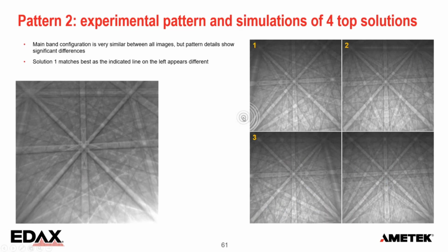Here's another one. On the left is the experimental pattern. And the patterns on the right already look a little bit more similar than what we had before. But now here in the experimental pattern, you have this band here and this one. They look about the same, but this one is a bit blurry in the middle. So this looks like it's one of the other types of bands. And when we look at the simulations, top and right here are the same. Here the top and the left are the same. The one on the right is different. Here on the left is different. Here on the top is different. And here they are all three the same. So again, indicated with this overlay, where are the similar ones?